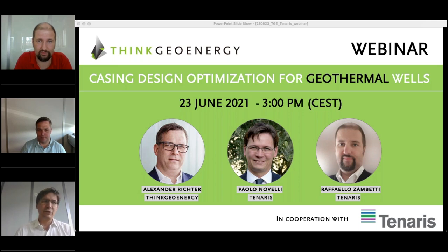Yes, there are. There is some study. I would say that the limiting factor is mainly the material itself. If we stay with epoxy phenolic coating, the limit will be around 200, 250 degrees C maximum. There are other plastic materials which may have a resistance above that, or we can go to ceramic coating, which is a field that has been explored and grants a higher temperature performance. The main issue there is always the economical balance between the material that we select as a coating and the cost that we are going to have on the well. So there are ongoing studies. I don't think there is a solution nowadays for that.